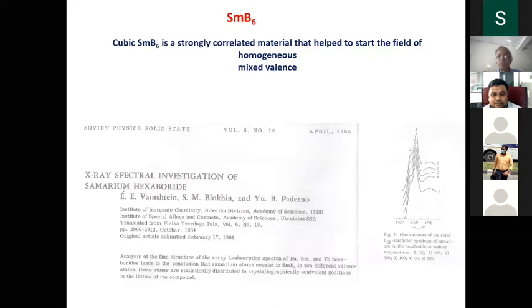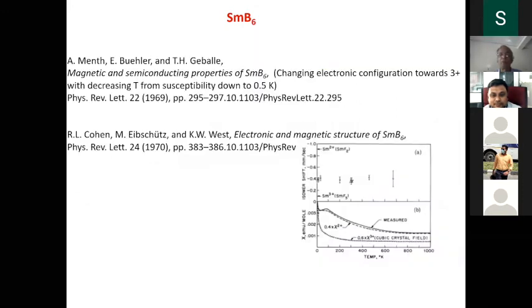And then the field advanced, and a better understanding developed. Subsequently the susceptibility was studied by some groups, and samarium Mössbauer was studied here. You know, samarium Mössbauer measures the s electron density at the nucleus of the atom you are studying. So the s electron density at the nucleus, basically measured by isomer shift, plotted here, is a measure of the valency of any element you are talking about. The valency is different, isomer shift is different. It refers to some reference material. Okay, in this case, it is samarium with reference to samarium trifluoride, which is trivalent.